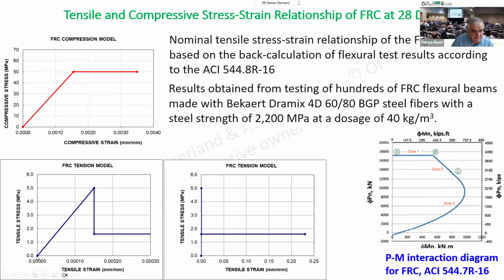The model for tension, we consider about 10% of the compression. Now it can be even 12% with the fiber. So that's 5 MPa. It is linear, then we have a drop, and then it plateaus. How we can find these things: either from the mixes based on our experience, or using ACI 544.8R, which tells you how to back calculate and build these models from the test results. And based on this data, we can build our P and M interaction diagram.